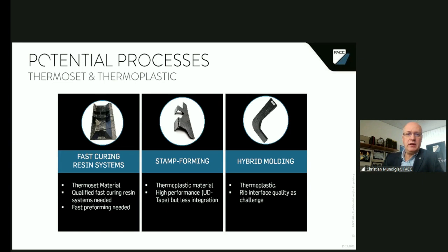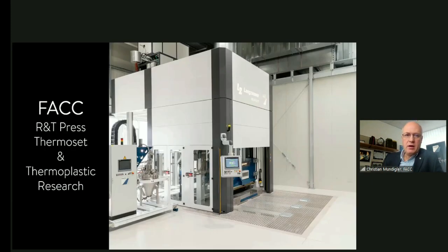When it comes to thermoset and thermoplastic, we invest heavily in fast curing resin systems, like thermoset material qualified for fast curing resin systems, and fast performing is needed, of course. Stamp forming for less integration using unidirectional tapes. And when it comes to hybrid molding, for thermoplastic rib interface quality is a challenge, of course. Here you can see our research press for thermoset and thermoplastic, but we have three big ones for production already in process.